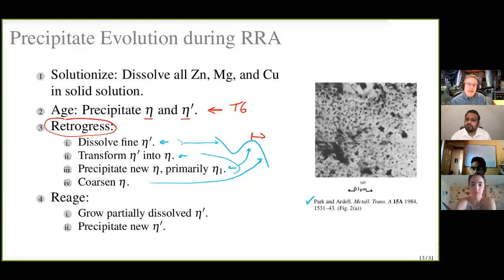And that's also a problem I expect they will have with the hot forming processes they're trying. I didn't talk about that, but there's a very good chance you could have some significant coarsening effects during the hot forming if you're not very, very careful. So again, people are working on hot forming in development efforts. There are a lot of challenges there. So I think if you can get away with 20-25% ductility, our retrogression forming reaging is better for that niche.